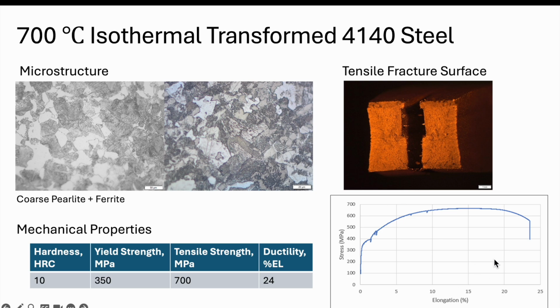So here's our engineering stress strain curve. Again, we see the yield point phenomenon. We see a major drop in yield strength. We're down to 350. Same thing, tensile strength goes down to 700 or so, and the ductility is highest. So we're at about 25% elongation at fracture. And the hardness, this is our lowest as well. So we got about 10 on the Rockwell scale. Again, if our experiment goes bad and we quench before we get perlite, this number shoots up. But in fact, the microstructure here, perlite, corresponds to the very low hardness that we see in this case.